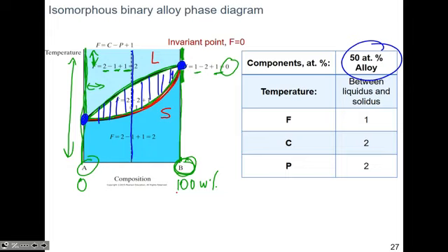It's just very schematic right now. But here, if you have, let's say, 50 atomic percent, that means you have 50 AB. So your stoichiometry is something like this. It's 1-to-1, right at this dash line that I've drawn over in blue. That means AB coexists as some liquid and some solid, depending on the temperature. So if you're here, is there more liquid or more solid for this AB mixture? Versus if you're down here at a lower temperature. So that's what we'll talk about today, actually quantifying that.